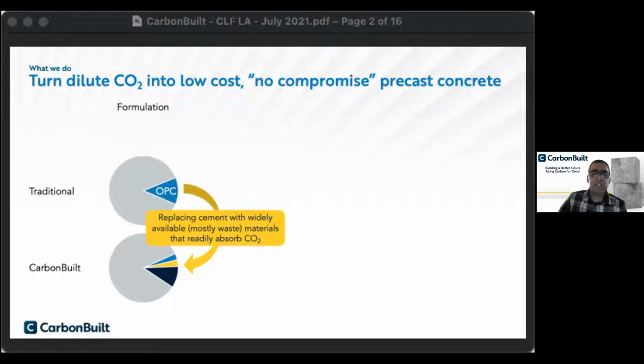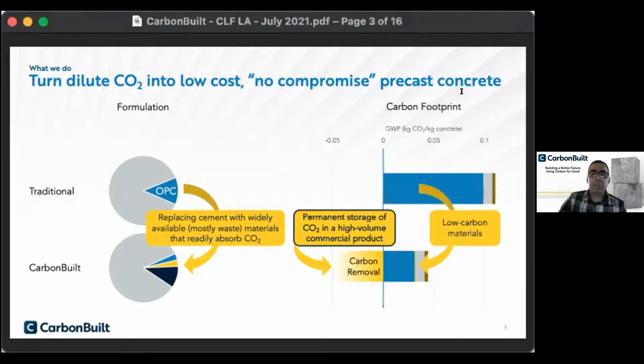Okay, we do this first by making a change on the formulation side, and that involves substituting most of the Portland cement with a range of widely available and mostly waste materials. When cured with CO2, and it's a substantial amount of CO2, we can meet concrete's performance requirements while substantially reducing the carbon footprint. And that reduction happens in two ways.